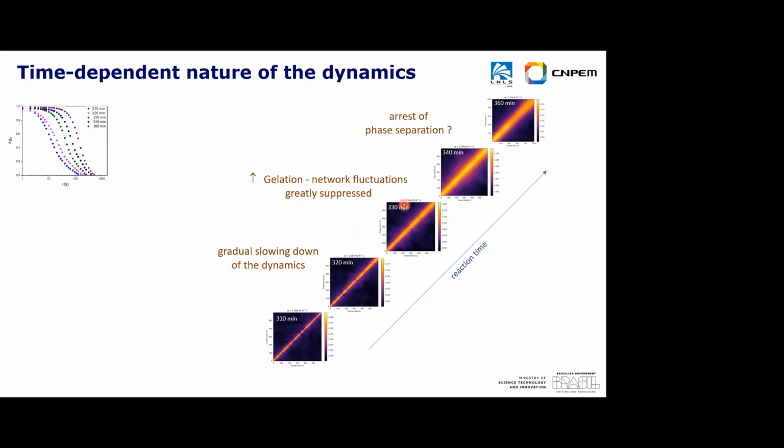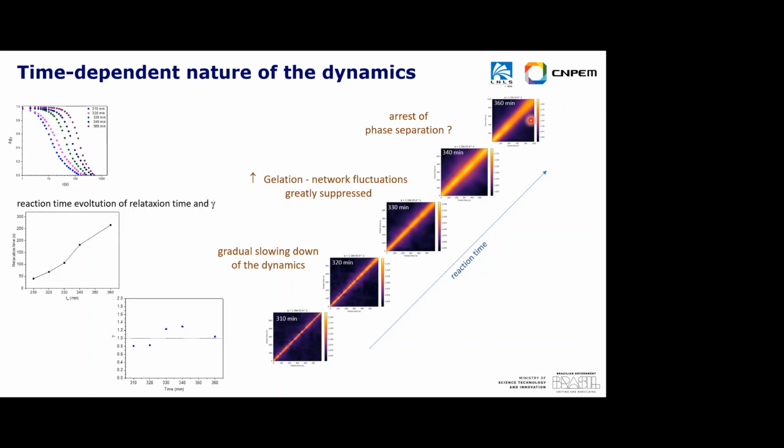So we believe this is because we had phase separation at the same time as the gelation. During the gelation, you have the formation of the gel network, and at the same time the phase separation. Once you arrive at the gel point, it freezes the phase separated structure inside. We have an equilibrium system again. Things are really, really arrested there. They do not have much motion. So it can give us information about when it occurred.